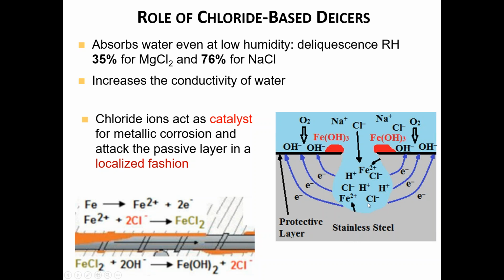And that basically further accelerates the corrosion. Again, the localized corrosion is much more problematic than the general corrosion, also known as uniform corrosion. So in other words, it's hard to just say, hey, if I know it's corroding at 1 quarter inch per 5 years, let's just design it to be thicker. That really doesn't work in these kinds of scenarios, because the localized corrosion rate at that spot is usually 5-10 times faster than usual. And also it's hard to predict.